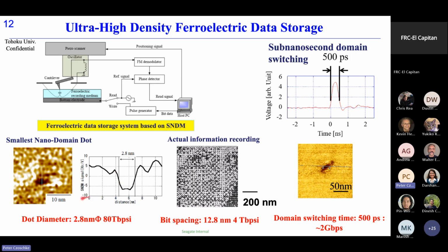If we can form another bit in the vicinity of this dot, the memory density will reach 80 terabits per square inch. But actually, this very tiny dot was formed by using a very thick tip with a tip diameter of 50 nanometer, like this. So if we apply the electric field here, the two dots are merged, unfortunately. Anyway, so, but we also tried to store the actual information. This recorded pattern is composed of the positive and negative domain dots, and the bit size is about 12.8 nanometer, corresponding to a memory density of 4 terabits per square inch.